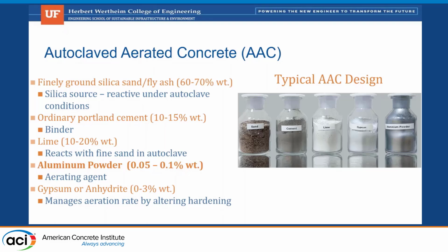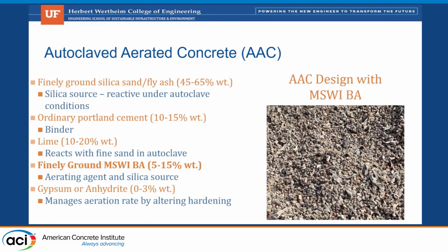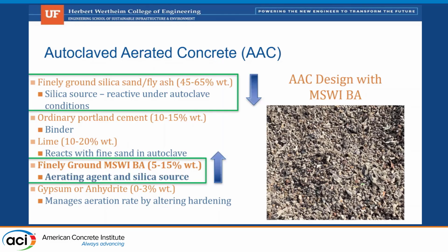And then we'll also add some gypsum and anhydrite. Our particular design is we obviously were replacing the aluminum with MSWI. So we had to increase the weight of that because the pure aluminum obviously has a lot more aluminum, where MSWI has a fraction of aluminum. So we were also able to replace some of the sand as well because that's present in the MSWI.